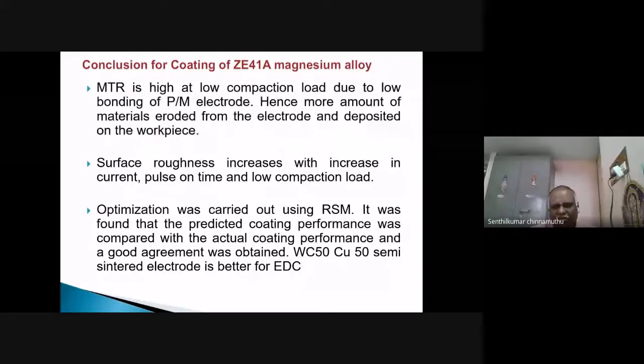Optimization was carried out using RSM, and it was found that the predicted coating performance, that is what we obtained at the optimized value, compared with the actual coating performance, showed good agreement, within plus or minus 10, which is statistically significant. And the tungsten carbide 50%, copper 50% semi-sintered electrode is better for EDC, because the semi-sintered electrode dislodges more material, and the coating is thicker than that of the sintered electrode.